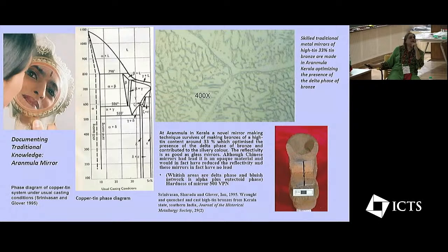So in fact, you find that in normal conditions, you don't really find too many high-tin bronzes being used in antiquity because of this fact that as you keep adding more and more tin to copper, it becomes more and more embrittled. But it's quite interesting that in this traditional making of metal mirrors, they were very consciously aiming for a particular composition of tin in bronze at around, say, 32 to 33% tin, where what happens is that there is a predominant formation of this delta phase.